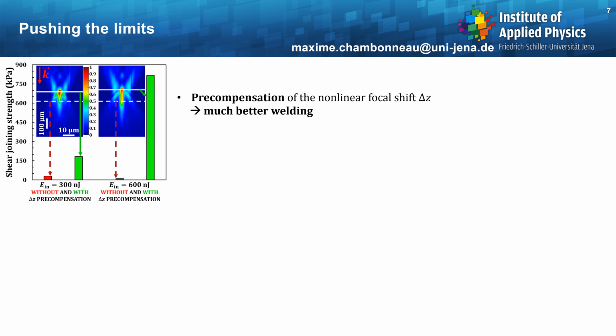Alright, so now that we know the behavior for the nonlinear focal shift as a function of the input pulse energy, we can come back to our initial problem concerning ultrafast laser welding of silicon and copper. Here in this figure, it is represented the shear joining strength for two different input pulse energies, without in red and with in green delta Z precompensation. And the striking feature here in this figure is that precompensating the nonlinear focal shift leads to a much better welding.